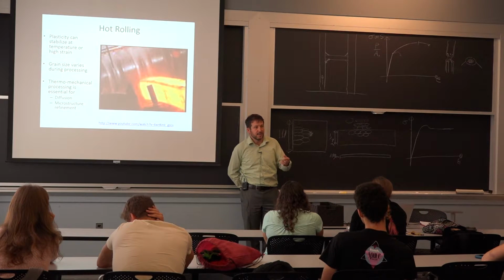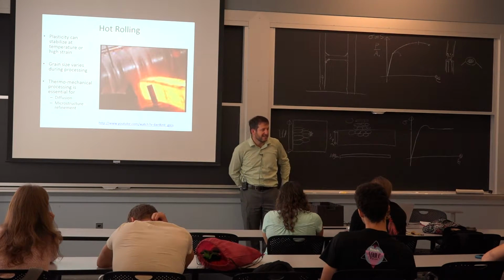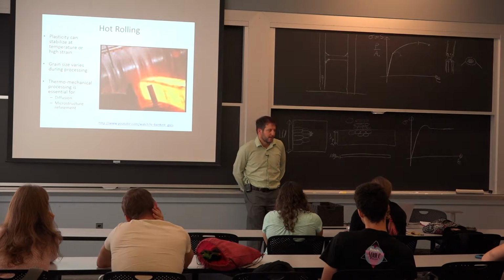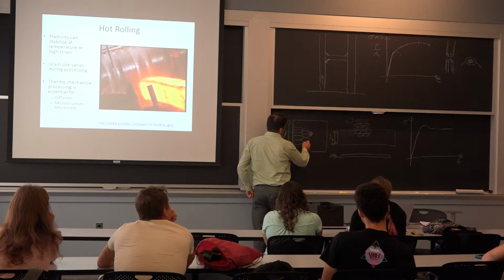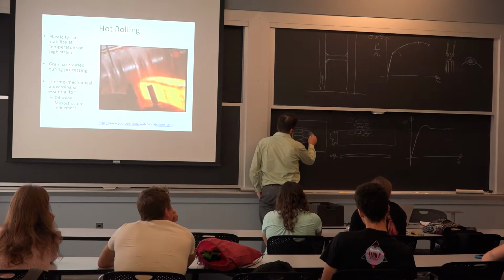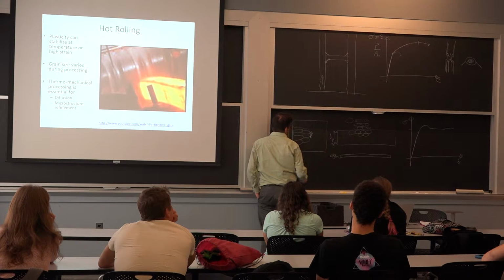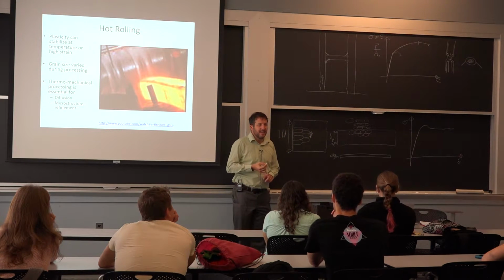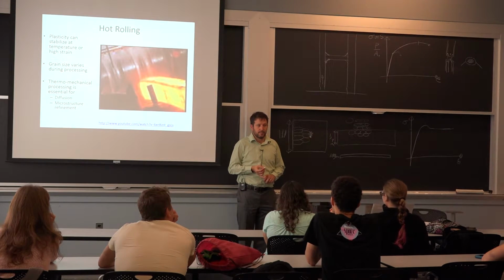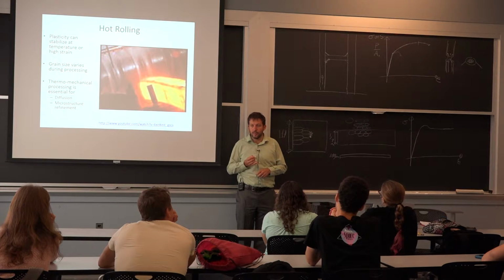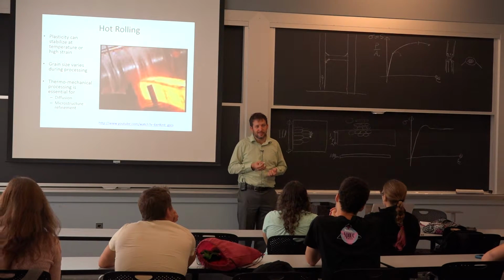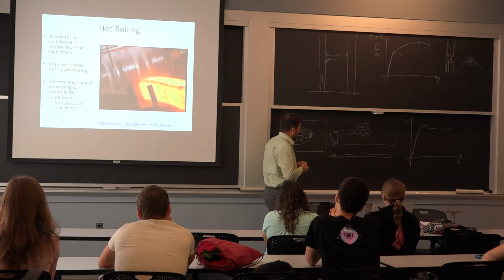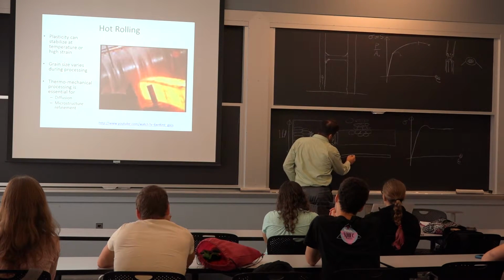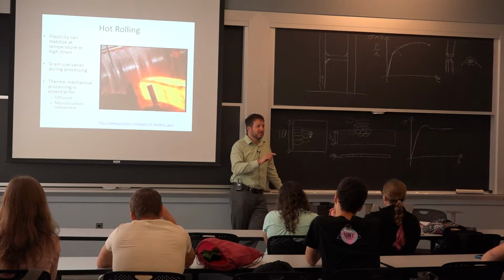So we make a good steel, but it forms these little ceramic pieces, essentially, if you want to think of it that way, that are part of that ingot here. So say I have a piece here that's the non-metallic. Well, it's not going to diffuse because it's stable at the temperature that we're rolling. It likes the way it is. So the only thing you can hope for is that it breaks down in smaller pieces. That's kind of ideal. If it does, then you hope that when you're very small, the inclusion remains significantly smaller than your product thickness. But there's no guarantee of that.